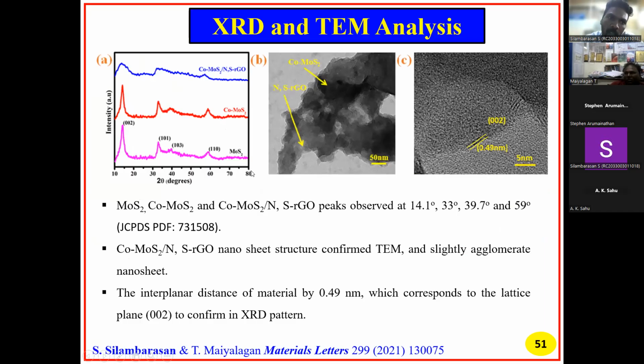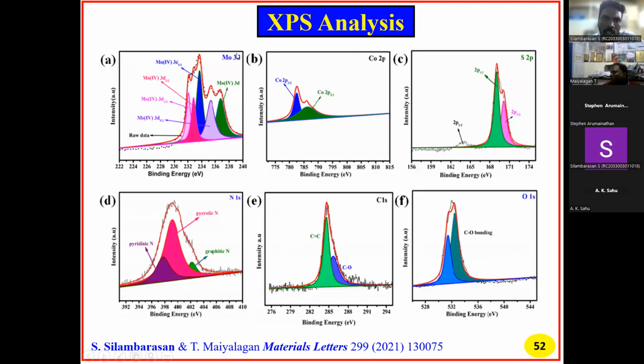In figure A, the XRD for MoS2 shows the intensity around 14.1, the plane is 002. Then cobalt-doped MoS2, compared to MoS2, shows a slight decrease in peak intensity and a slight shift. Next, for the composite with NSRGO, the peak intensity again slightly decreases and a peak shift is present compared to the pure and doped samples. Then figure B is the TEM analysis. Here the nanosheets are slightly agglomerated. Then figure C measures the interplanar distance, around 0.49 nanometer. The plane is 002.